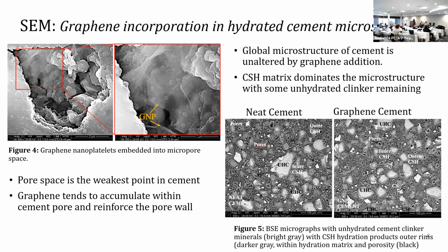So here is how that graphene looks in the cement after the cement is hydrated for 28 days. We always compare the neat, which is just class H with some bentonite, nothing else, and then the graphene. If you look at the bottom right, comparing neat to graphene enhanced cement, there is not a global difference in terms of hydration products. You still see a few unhydrated clinker minerals and it appears very similar.